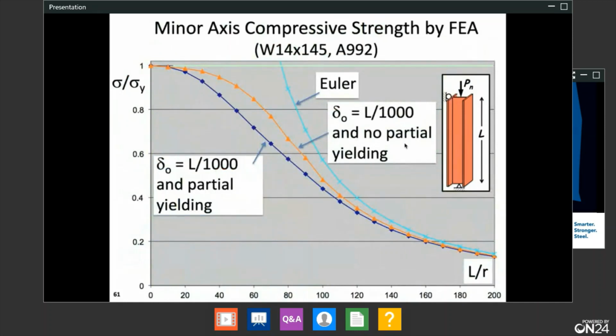Now, part of the learning module that I'm hoping you'll attack over the next week is to actually do a study similar to this one. Now, in this one, I used some pretty sophisticated shell elements, but you should be able to get similar results with MASTAN. And what I'm showing here is, on the horizontal axis, the L over r, and on the vertical, I've taken the stress in the column and normalized it by the yield. We started with full yield, we did Euler, then we just included the initial imperfection, but did not account for the residual stresses and the partial yielding, and then we went with the full GMNIA analysis, and we ended up with the red curve. And so our L/r of 50 was around here, corresponding to the 0.8, the 40 ksi failure that we're seeing, 150 corresponding to the 20%.